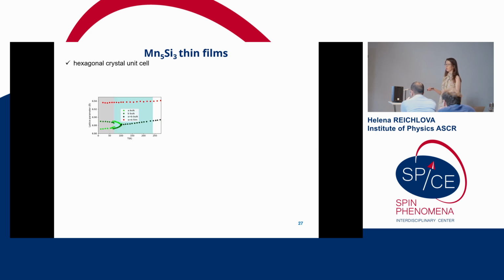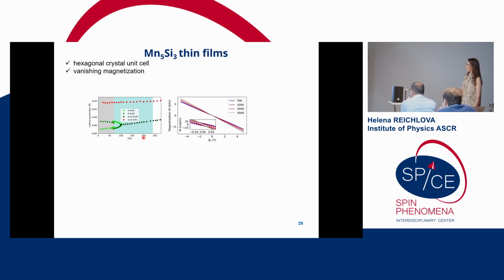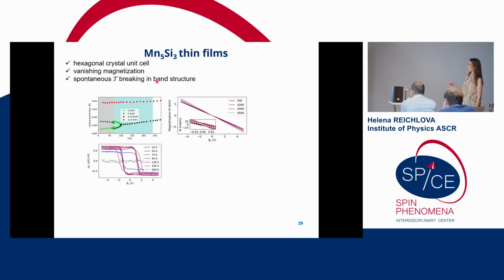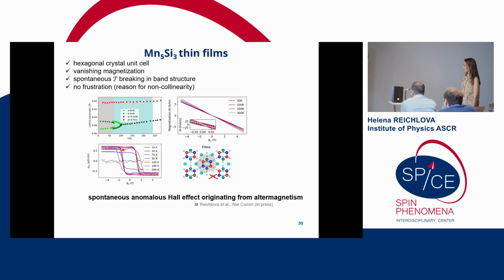And then let's just look at it. So what we learned: we have experimental evidence for the hexagonal unit cell, we have experimental evidence for vanishing magnetization, and we have experimental evidence for some spontaneous time reversal symmetry breaking because we do observe the anomalous Hall effect. At the same time, we know that our thin films are stabilized to this hexagonal unit cell in the full temperature range, which again allows us to compare it to the bulk material.